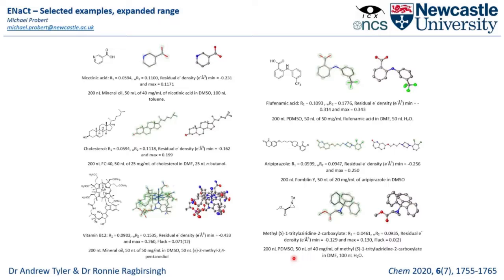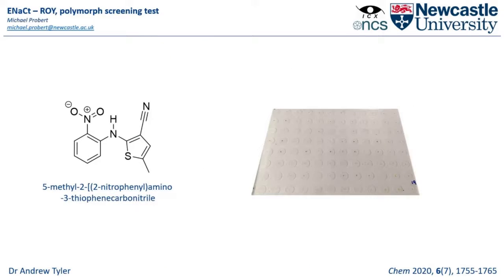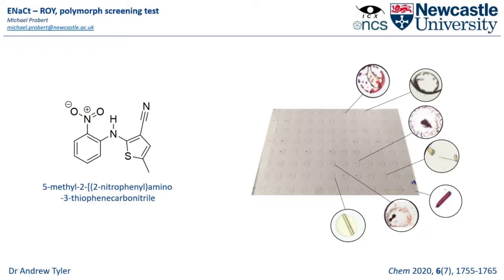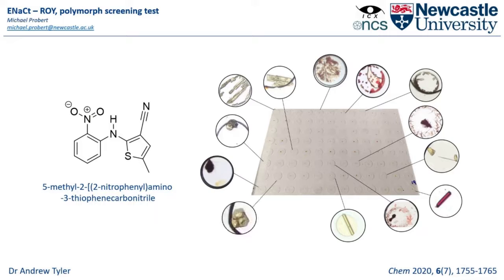crystallization analysis and looking for our result and interpreting our structure? Can we start exploring polymorphism? Can we look for changes in structure of the crystal whilst keeping this compound the same? And if we set up using the kind of king of crystallization, this red, orange, yellow ROY structure that's been analyzed over many years, and we set up a crystallization plate, we can see that we get crystallization of many different colors within the spectrum that we're expecting, and very many different morphologies.